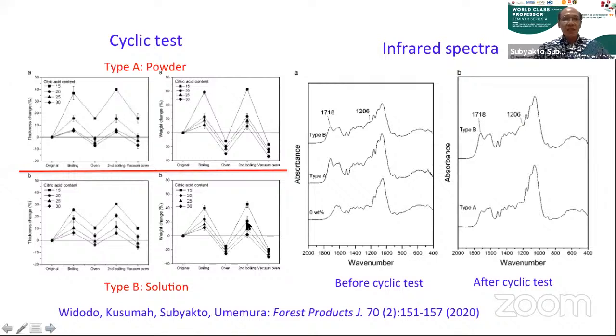And this is the cyclic test. This is a very severe test, and we boil, and we can see here that powder types have a lower water resistance compared to the solution type. And again, we check with infrared spectra here that we can find this peak for the ester linkage.